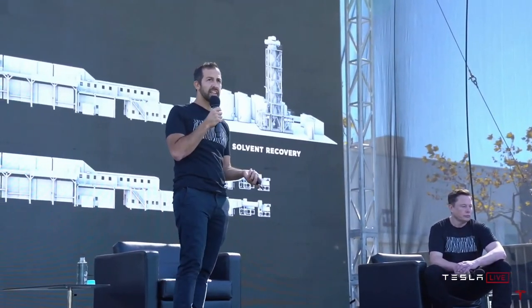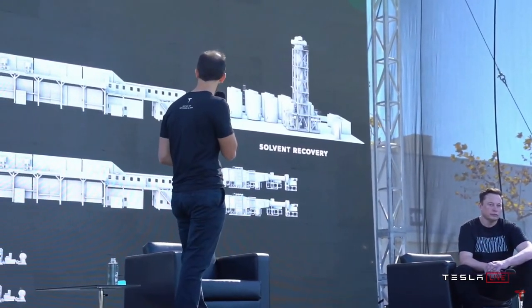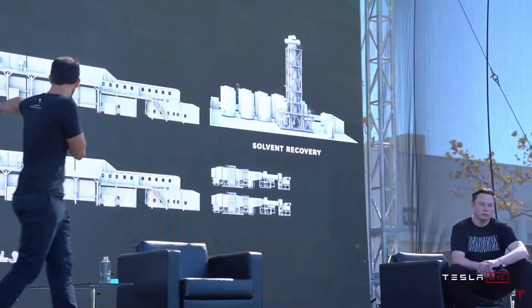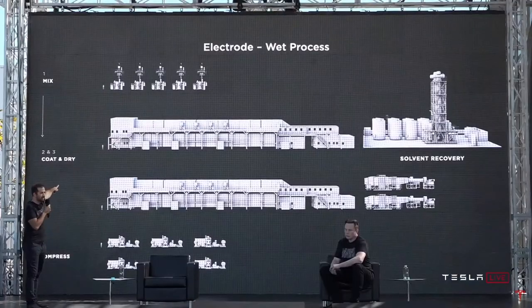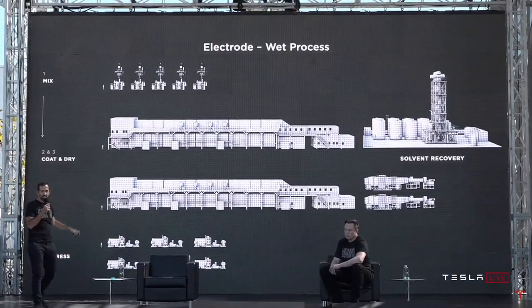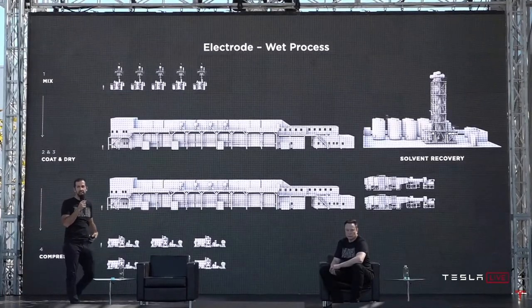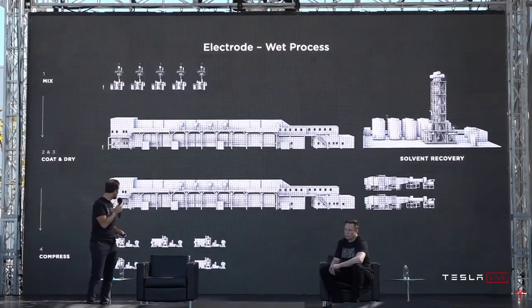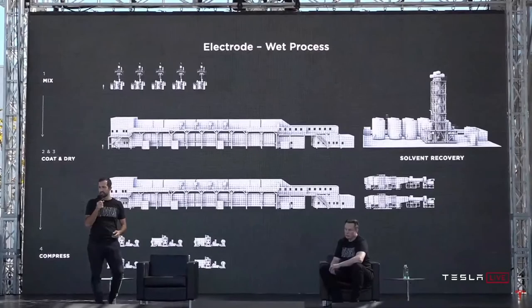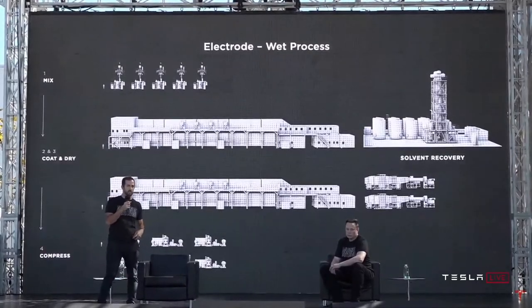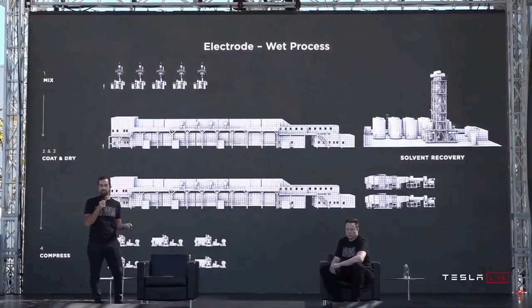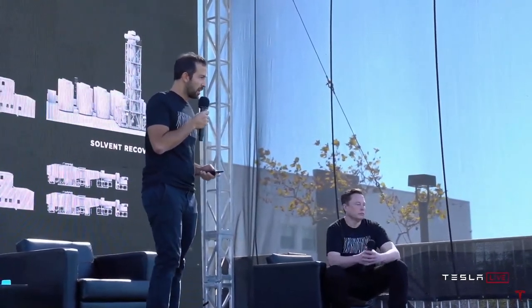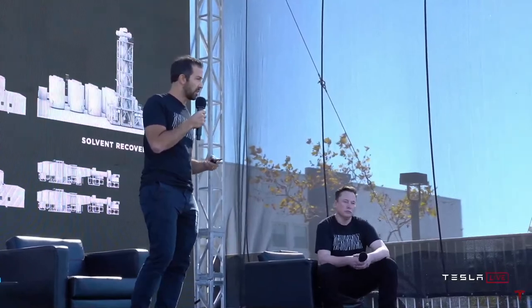And when you're looking at this, you're like, wow, that's a lot of equipment for one step, especially when you consider that little speck next to the coating oven is a person. This is serious iron involved in making batteries. Wouldn't it be great if we could skip that solvent step, which is one of those dig a ditch and then fill it kind of things, where you put the solvent in and then take it out and recycle it, and just go straight to dry mix to coat? And that's what the dry process really is about.